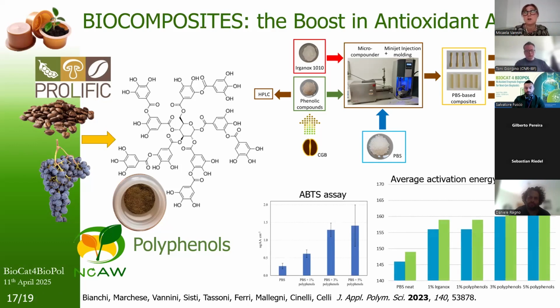obtained antioxidant materials as demonstrated with the ABTS assay. The antioxidant activity was comparable with that we recorded for our reference, PBS containing a commercial antioxidant material, in particular Irganox 1010. We used the Irganox 1010 in the same amount, and we obtained the same results.